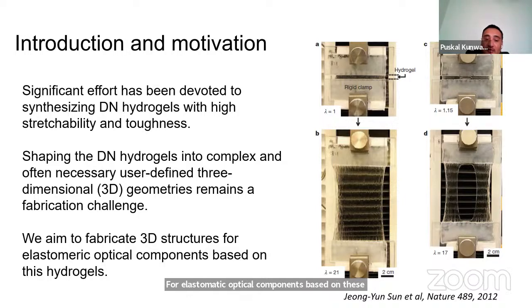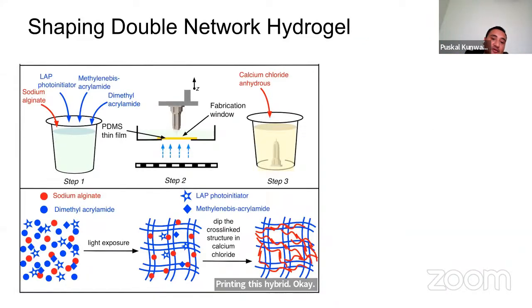Here they use acrylamide, which is photo cross-linkable, and the other network is an alginate network, which is ionic cross-linkable. So we aim to make optical components by printing these hydrogels. Now for PSLA, what's required is that your liquid has to be in solution form. But as soon as you add, for example, calcium ions to sodium alginate, which is ionic cross-linkable, it readily cross-links and forms a gel. So there you cannot use that. You can cast it, but you cannot really 3D print it, especially with projection stereolithography.